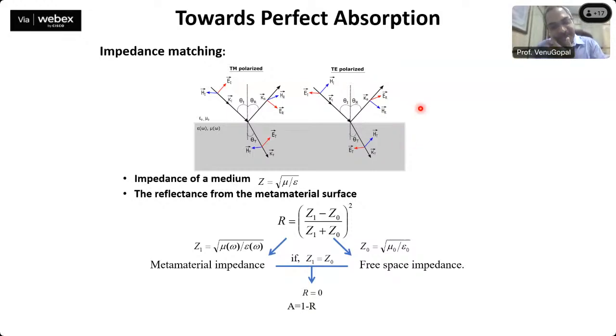So if we have an impedance matching layer, then we have the active layer, and then we have the top and the bottom thick metal layer, which suppresses all the transmission. Once we suppress all the transmission, and we are already suppressing the reflection because of the impedance matching top layer, then all the light will be absorbed within the thin absorbing layer, which is in between these two metal layers.